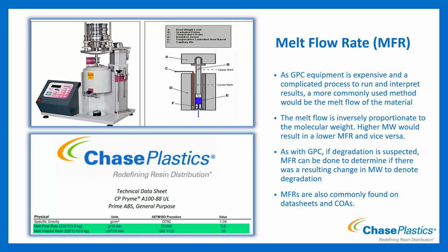But melt flow rate is a good indication because it is inversely proportionate to the molecular weight. So if you have a higher molecular weight material, you've got more entanglement that's happening, you're going to have a lower flowing material, so lower melt flow, and vice versa. So if you've got a lower molecular weight, it's going to have a higher flow. So if we suspect degradation has happened, we can take the melt flow of the control and compare it to the part and see if there's been a change, an increase maybe for hydrolysis, decrease maybe for cross-linking, and we can compare that. Melt flow is also a much more common test.